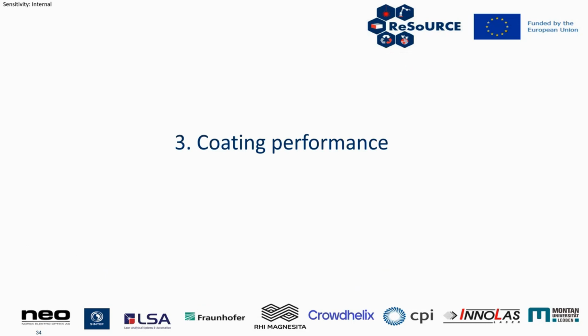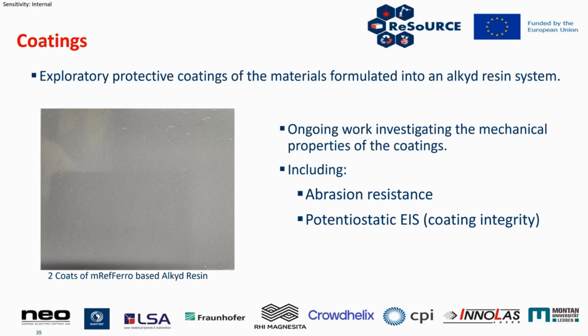Another application we looked at was performance coatings. So we've started exploratory protective coatings using an alkyd resin system. What you can see on the left is the coverage that is possible with just 2 coats of the mRefFerro material on a sheet of steel. So we can get good coverage and a nice base layer. We've got some ongoing investigations into the mechanical properties, looking at abrasion resistance and wear resistance of the coating. Can we make a tough coating out of this to protect the steel? We're also looking at potentiostatic EIS, looking at the coating integrity, to see whether it could be used as an anti-corrosive coating, or whether it would just be a decorative base coating made with recycled materials.